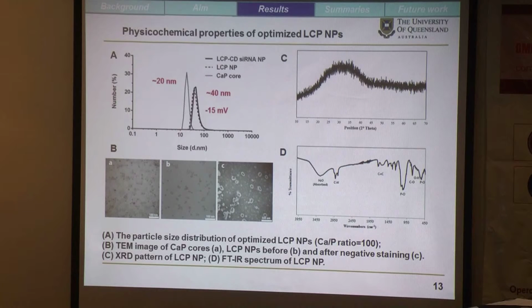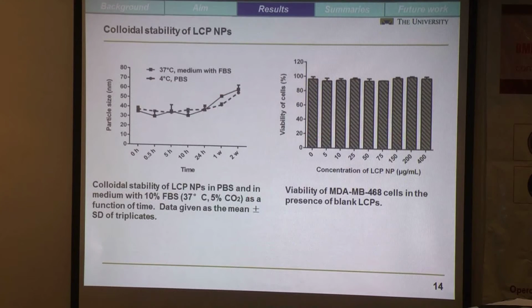And the TEM picture confirmed the hollow spherical structure of the calcium phosphate core and the outside lipid coating membrane after negative staining. In addition, the XRD pattern and the FTIR spectra confirmed the amorphous calcium phosphate phase in the LCP nanoparticle. So what's the colloidal stability of the LCP nanoparticle we synthesized with negative charge?